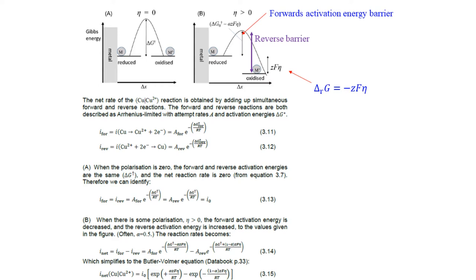If the polarization eta is positive, that's the same as saying that the Gibbs energy of the system decreases by an amount ZF eta when the metal goes from the metal phase to the dissolved phase. Now, the effect of this in the picture is that because there is a total energy drop ZF eta, it's no longer the case that the forwards and backwards energy barriers are the same. The forwards energy barrier becomes a bit smaller, and the reverse energy barrier becomes a bit bigger.